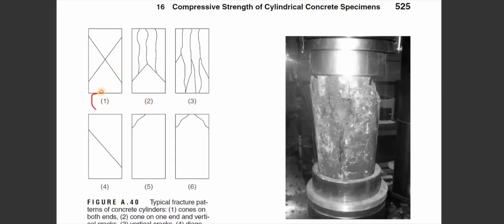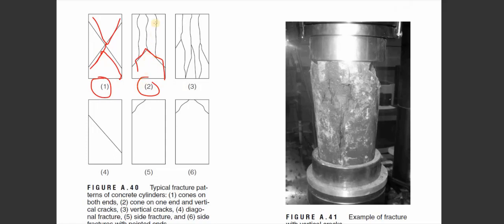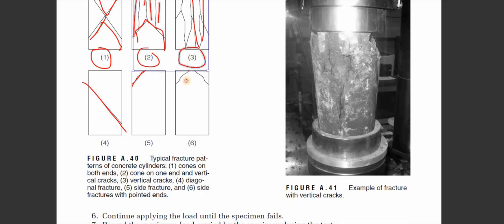The first type we call cones on both ends. We find clear cones on top and bottom. The second one is a cone on one end and vertical cracks on the other. Number 3 is vertical cracks only. You cannot distinguish any cones here. Number 4 is diagonal fracture. Number 5 is side fracture at top or bottom. And number 6 is side fracture with pointed ends.